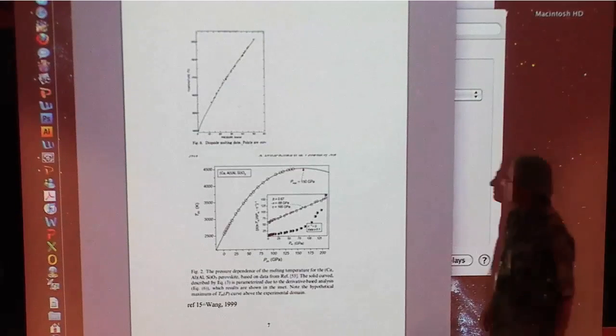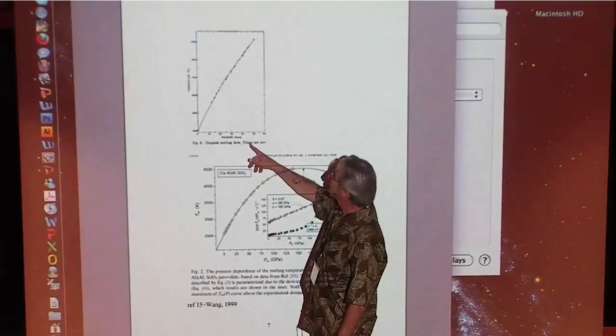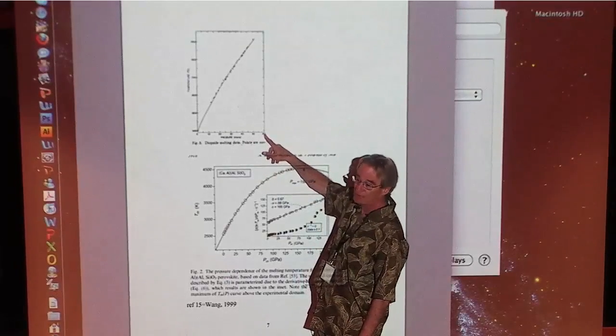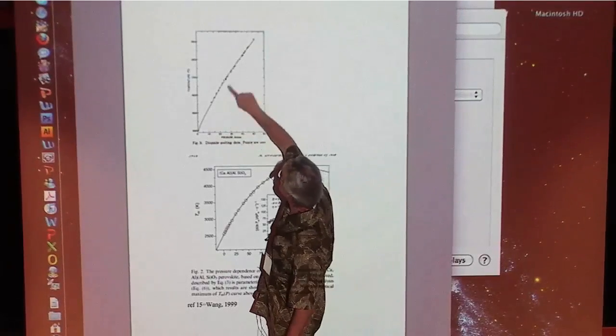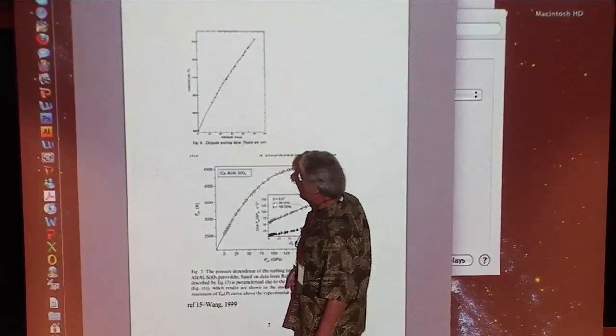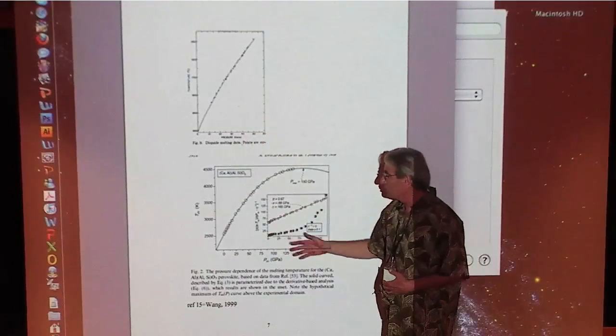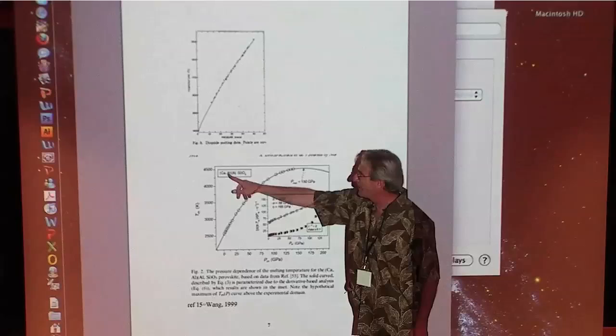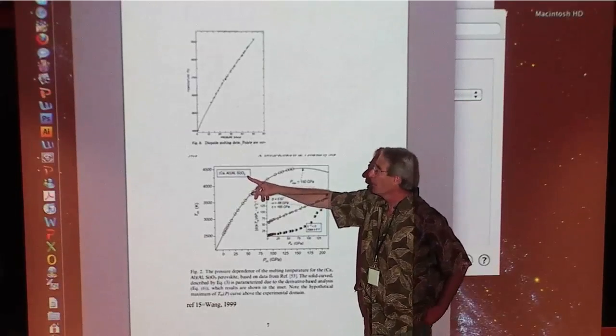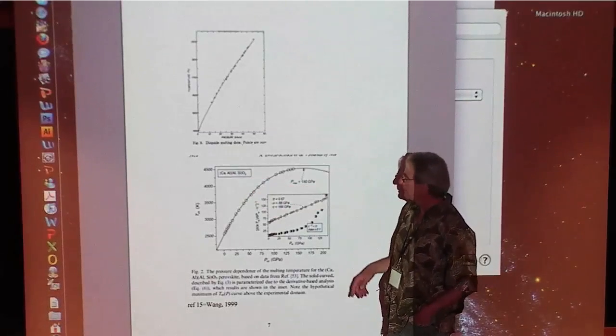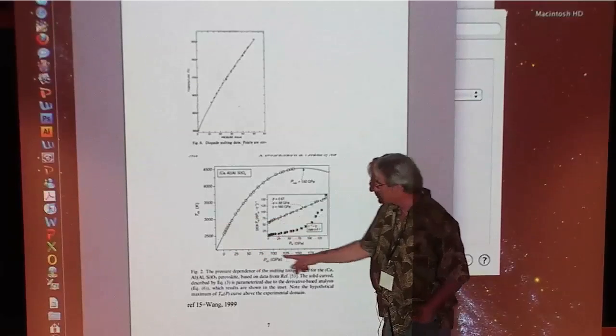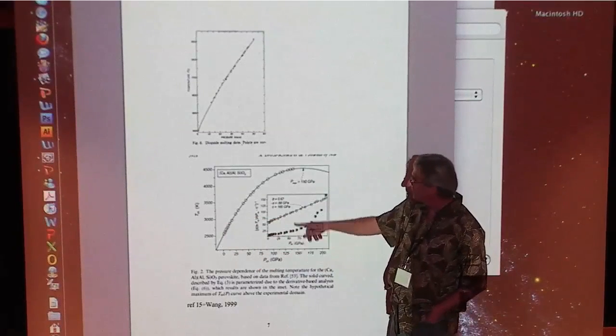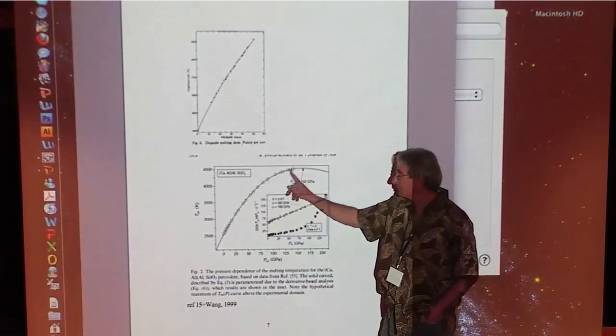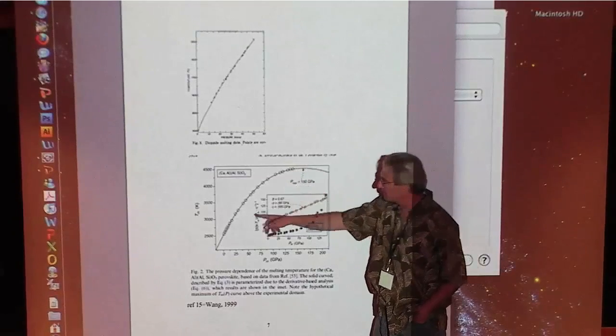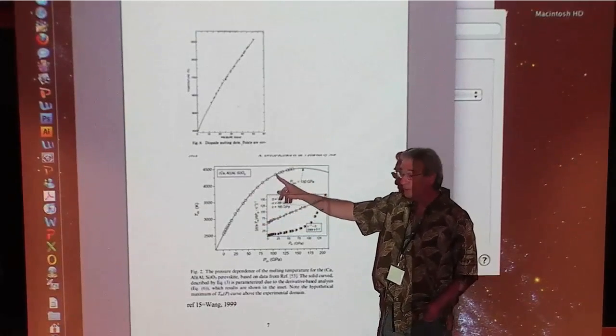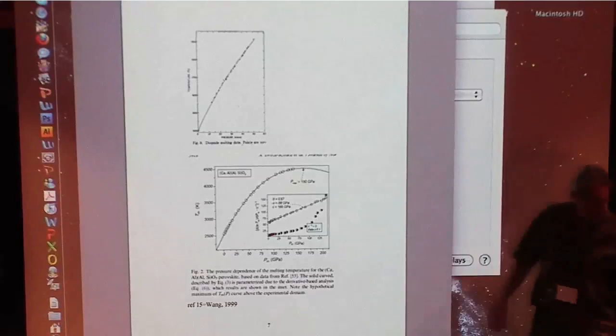I'll show you a few others. Here's from the old days, Boyd and England, diopside melting. This is actually in kilobars, this is 8 GPa here, and you can see a little bit of curvature. But let's go to some more recent, more robust studies. This is calcium aluminum perovskite, CaPV, and this is again temperature, this is pressure. Here's the core-mantle boundary. And look at this, these are the data. This is a fit, but these are the data. Clearly, this melting curve is flattening.